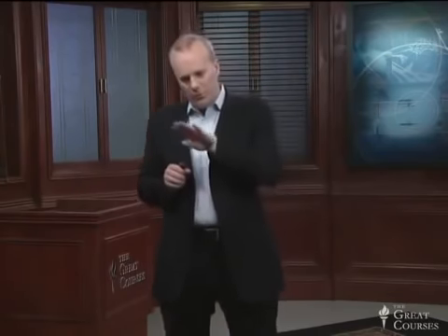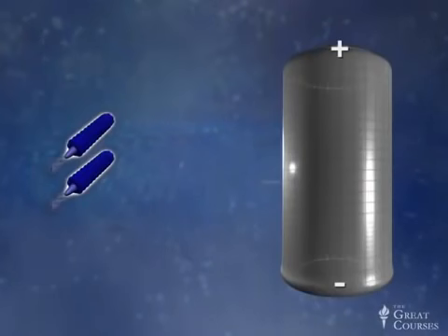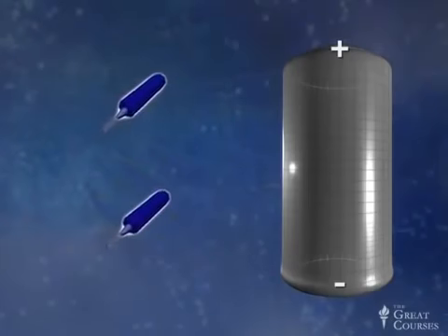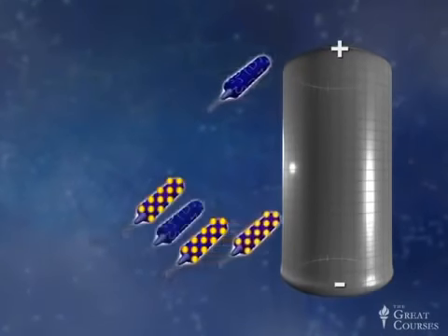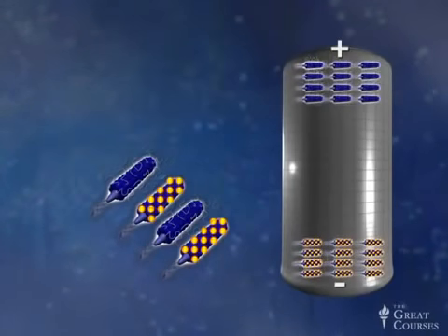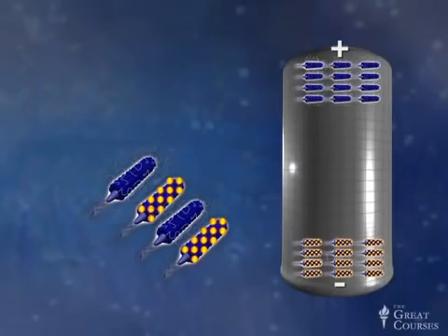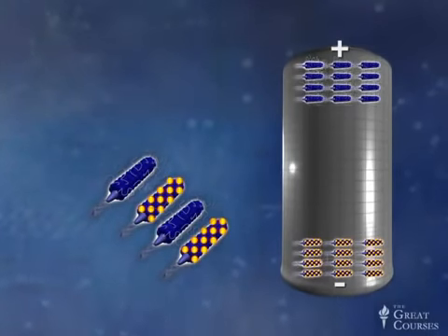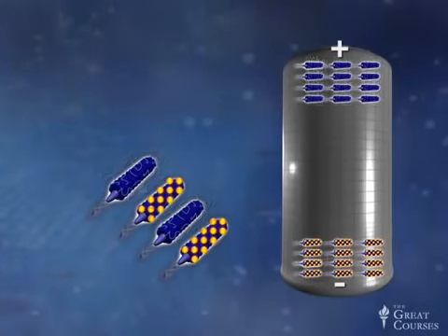Now, of course, making a battery is more than just making one wire, which these viruses effectively had become. They needed to put them down onto a substrate. They needed to make a practical device out of them. And they found the conditions under which they were able to coat onto just a flexible piece of plastic, effectively, their viruses. And by managing the charge on the viral particles, they were able to ensure that the virus assembled into nice, smooth, what are called lamellar structures. So there are these kind of stripy patterns of viruses with their coatings of nanoparticles of cobalt oxide and of gold on top of them.